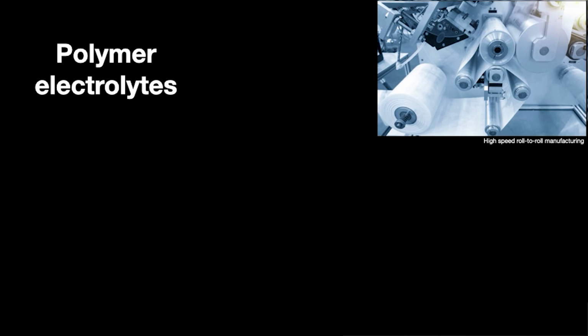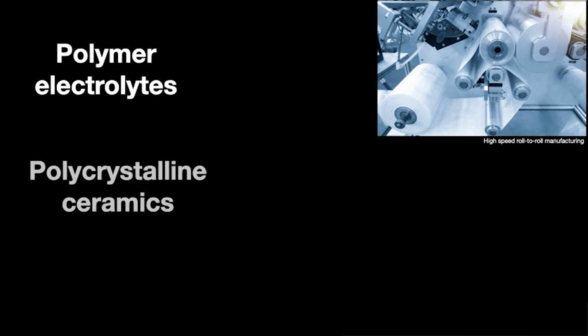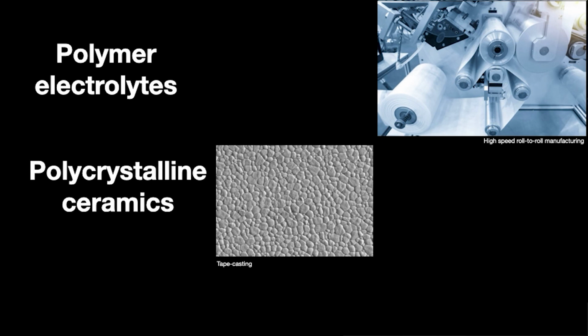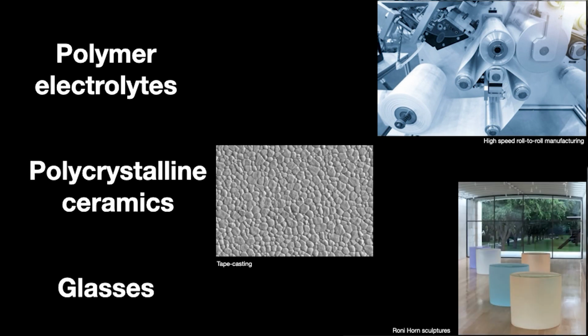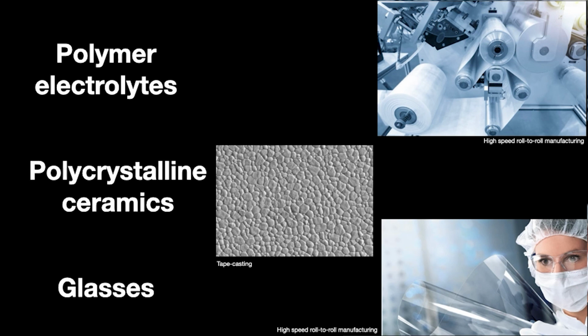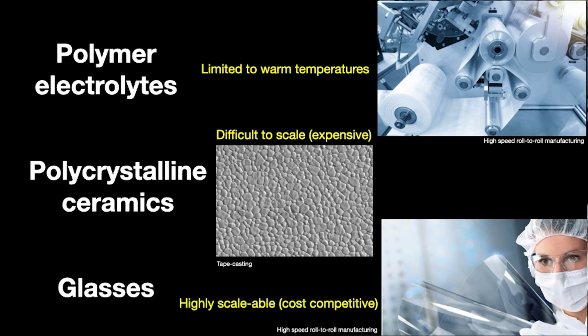Clearly, polymer electrolytes are one, and these are commercial lithium polymer batteries. It has a big advantage of being high-speed roll-to-roll manufacturing. Polycrystalline ceramics are getting a lot of attention. That's typically done through tape casting. And glasses, of course, are also a high-speed roll-to-roll manufacturing process. Anybody carrying a smartphone has a very thin glass display, and those are produced at scale at very high volume. So what are the downsides? Well, polymer electrolytes are typically limited to warm temperatures, right? The conductivities are not very good at room temperature and certainly not below. Polycrystalline ceramics have advantages electrochemically and mechanically, but this is a difficult technology to scale, and it tends to be expensive. Glasses are already scaled, so they scale similar to polymer electrolyte. So there are some big advantages to glasses.